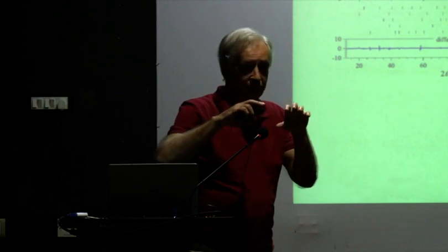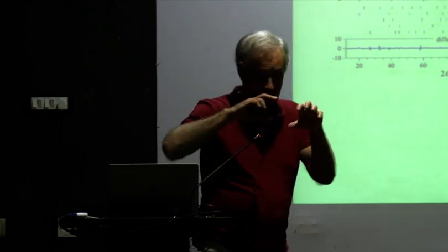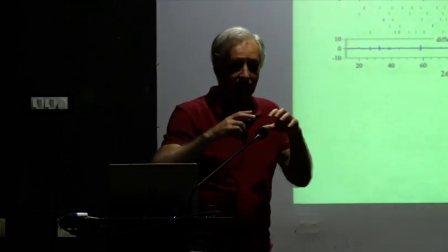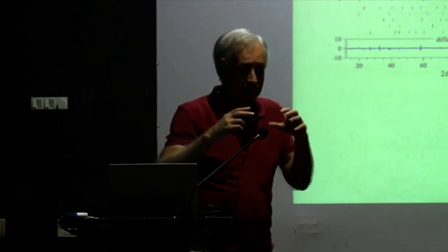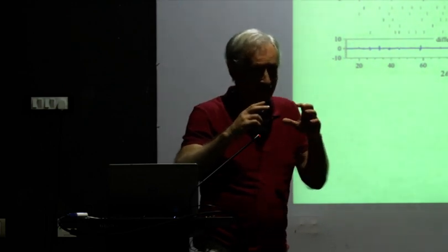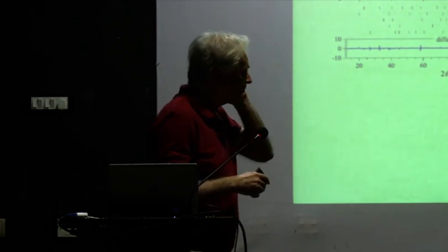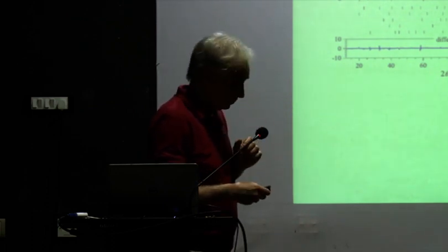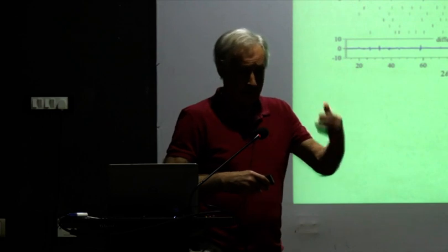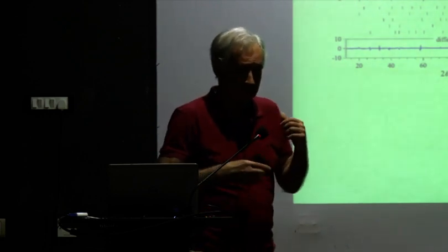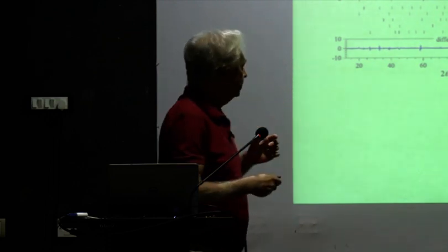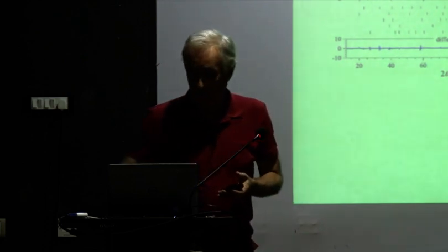And when we have such coexistence, we have strains. Of course, we have small volume parts and large volume parts in the sample, and they have to match somehow crystallographically. And to match those will require the presence of strains. It gives rise to a strain state. So this also accounts for the hysteresis that we see here. Because of these strains and things, we see the hysteresis in the field dependence of the magnetization.